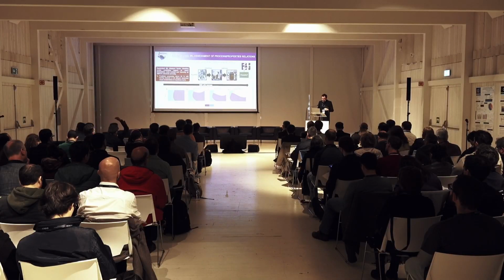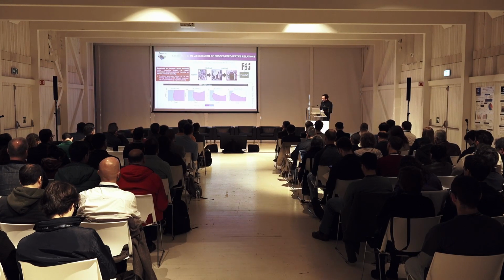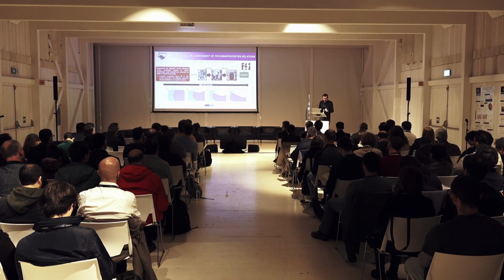Okay? We didn't use any unsupervised technique here to identify the classes and so on. This was really human-based. Still, this revealed very useful. At that time, this model had 80% accuracy. That means that when you enter into the model some intended manufacturing parameters, like the intended formulation, solid content, and viscosity, the model will make a prediction that in 80% of cases revealed to be correct when you do the experiments afterwards. Nowadays, 4 or 5 years later, it has an accuracy of 98%. Okay? A very simple model, which is being used every day by our technicians in our pilot line.